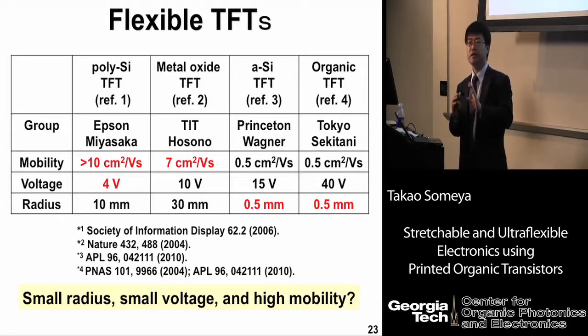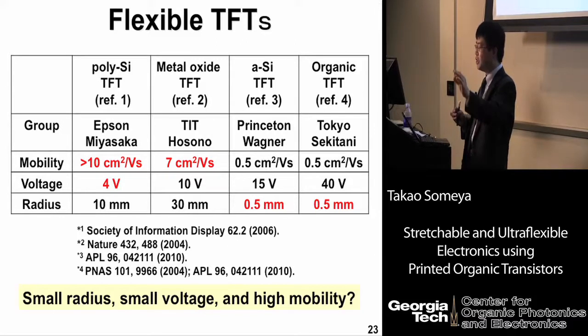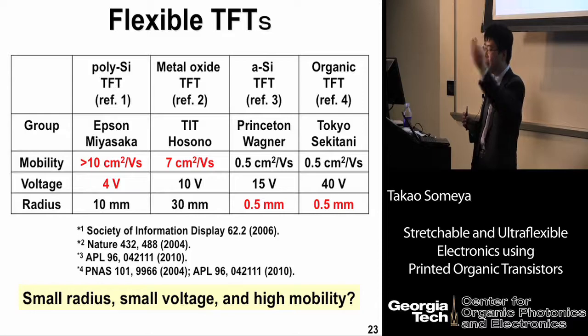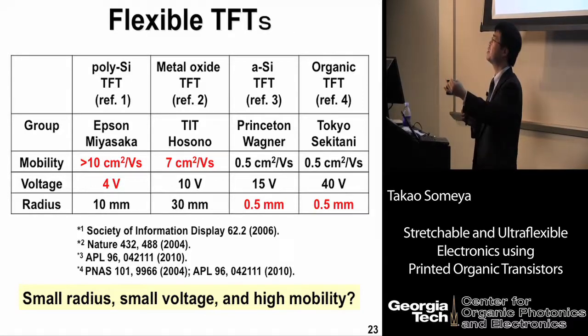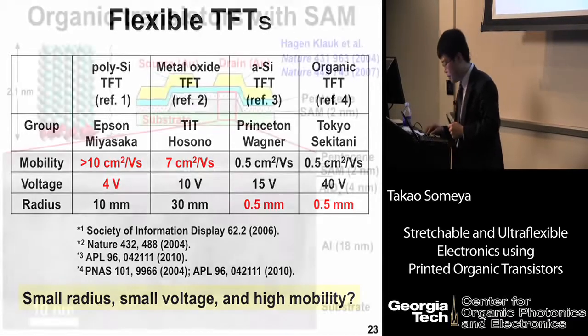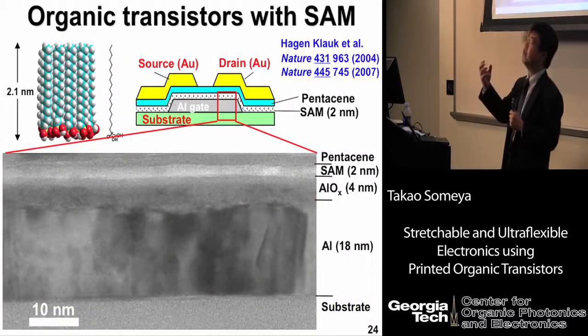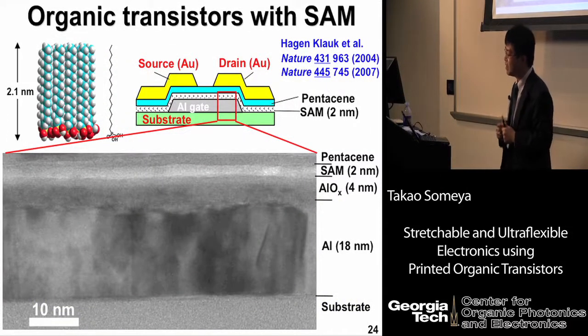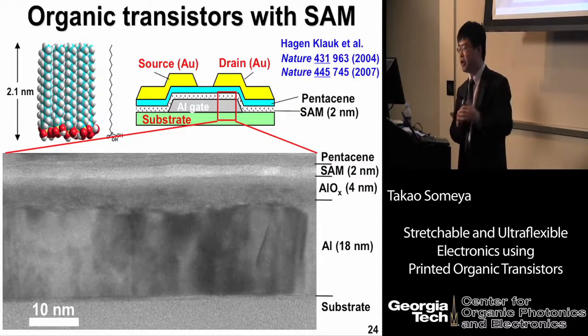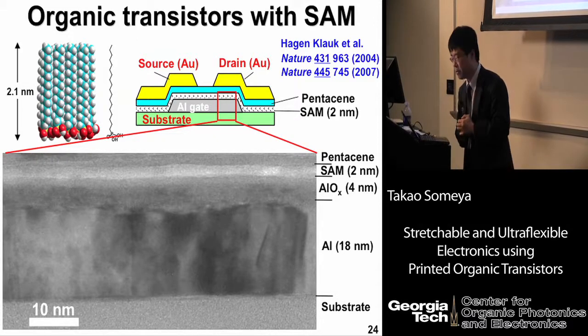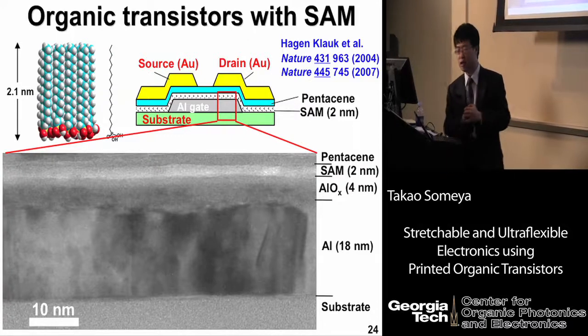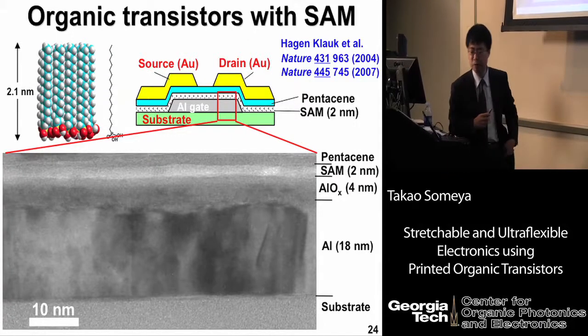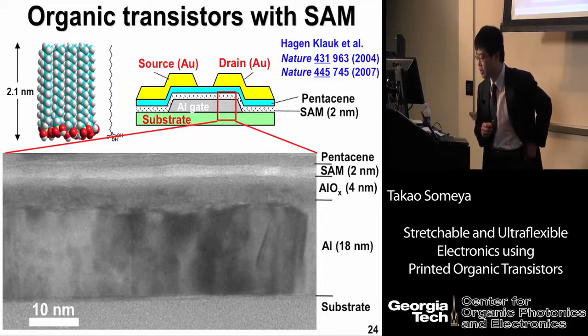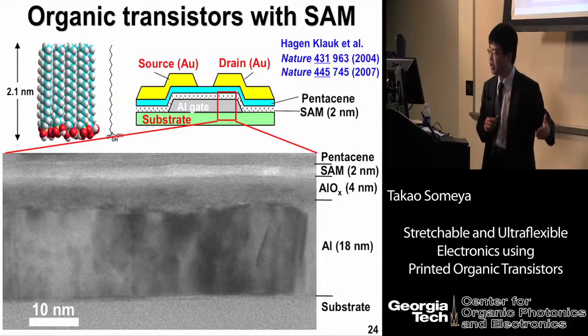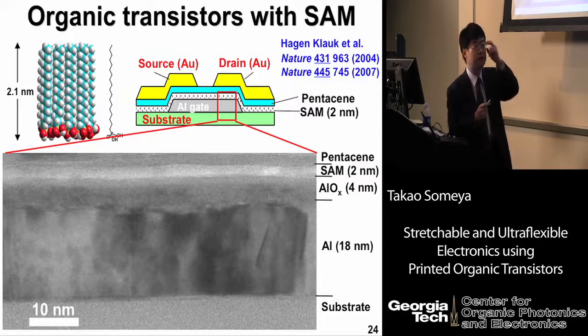It is extraordinarily difficult to achieve high mobility, low operation voltage, and sharp bending radius simultaneously. In order to achieve everything together at once, here is our preferred device structure. We use a self-assembled monolayer as the gate dielectric layer. Here is the cross-sectional TEM image and corresponding device structure.